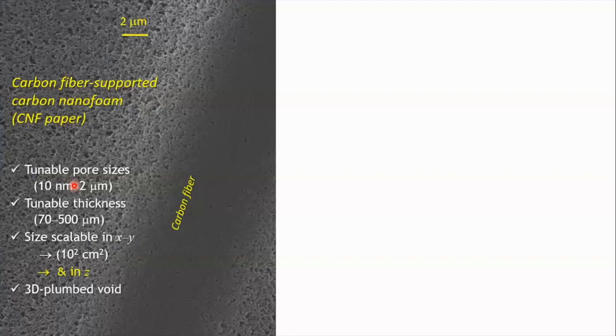So let's talk about carbon that could be an architecture and talk back to a macro scale contact. We've come out of a lot of our understanding through aerogel science, which is a whole series of talks on its own, but there is a polymer, an organic sol-gel process that gives you a polymer nanofoam that you can pyrolyze to make a reasonably conductive carbon. And rather than put it in a standard jello mold, in this case, a jello mold for us is carbon fiber paper. So rather than trying to span across a centimeter or a meter, because sol-gel science is very scalable, our mold is going to be carbon fiber paper. So here's a carbon fiber that you can see, and you can see the high quality adhesion of our pyrolyzed polymer nanofoam there. Now, the fun thing about sol-gel science, it gives you a way to map different pore size ranges that's co-continuous with that solid carbon.